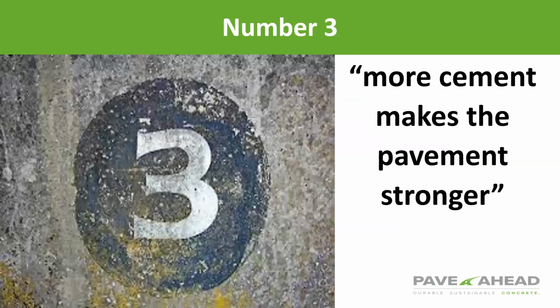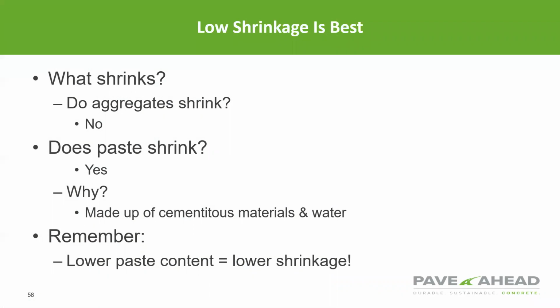So we're down to number 3, stronger concrete. It does help, but what shrinks is the paste, and the strength of the concrete depends on it. To increase strength, typically they add more cement, which is required for hydration. This means more shrinkage and potentially more cracking.